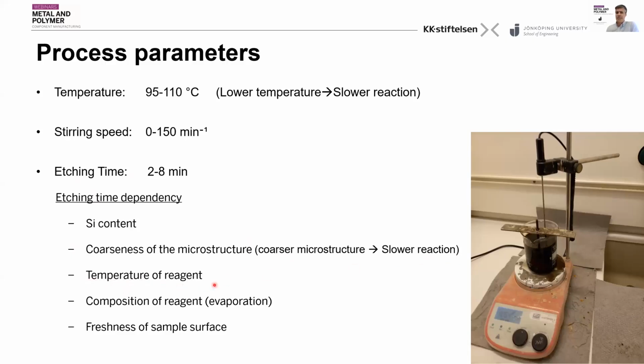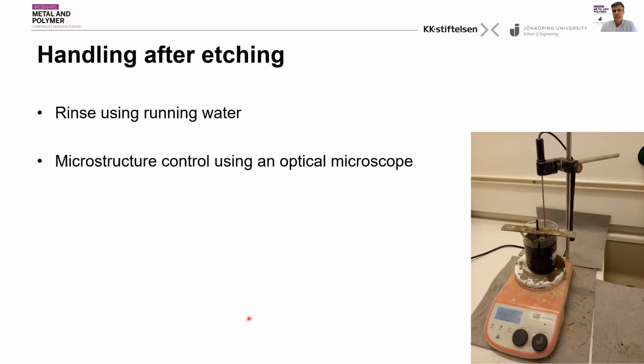It also depends on the temperature of the reagent and the composition of the reagent. During the process, we have evaporation of the water, so the composition of the reagent is changing, and that also influences the etching time. And also the freshness of the sample surface: if the surface of the sample is polished and then immediately color etched, the time needed for the color etching is smaller. We need less time. After the etching, we can clean the sample by using running water, and of course we check the microstructure by using an optical microscope.